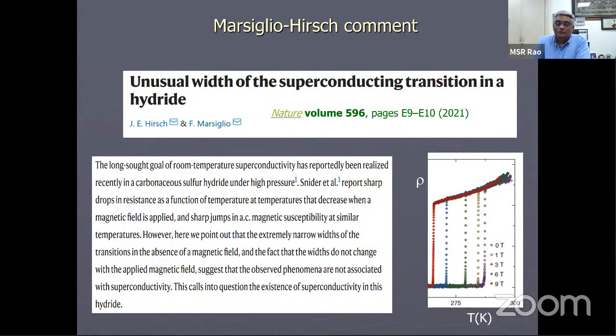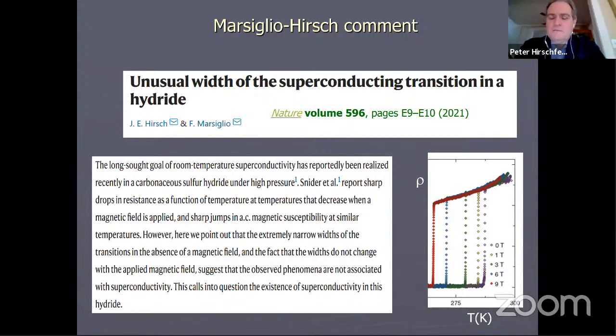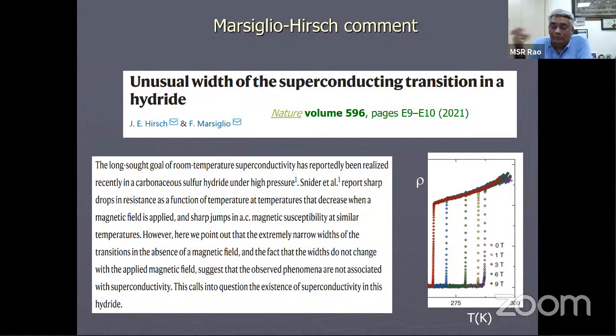As an experimentalist, I also feel that with the increase in field, there should be broadening. I don't have any problem with the sharp drop at zero Tesla, because even in a single crystal, for example YBCO, you see the delta TC is very narrow, less than 0.1, 0.5K. But then as you increase the field, you can say that you have very strong pinning in the system, so strong that even at 9 Tesla, even though there's a TC decrease, the TC doesn't vanish. But the fact that the field is penetrating so much, one can evaluate the penetration depth, and with that much penetration of field inside this superconductor, you expect some kind of broadening, the delta TC should change.